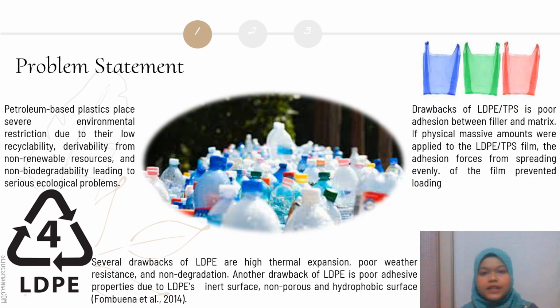The research interest in developing bioplastic material has evolved rapidly to resolve the petroleum-based plastic issue. However, LDPE also has limitations such as high thermal expansion, poor weather resistance, and non-degradation. Another limitation of LDPE is poor adhesive properties due to its inert surface, non-porous, and hydrophobic surface. Thus, starch was introduced to overcome the limitation of LDPE, particularly in degradation properties. The combination of LDPE and TPS, thermoplastic starch, is very attractive due to the good characteristics of both components.